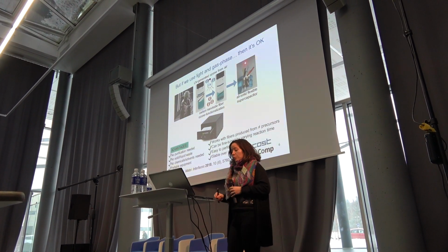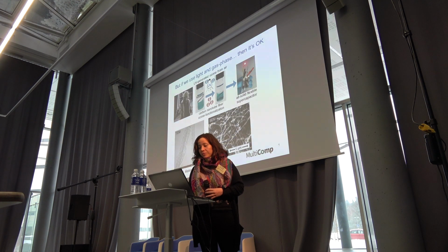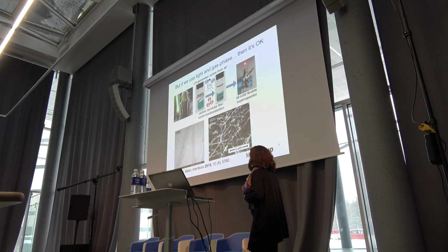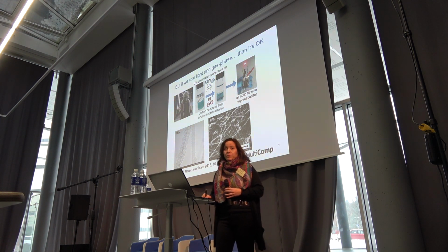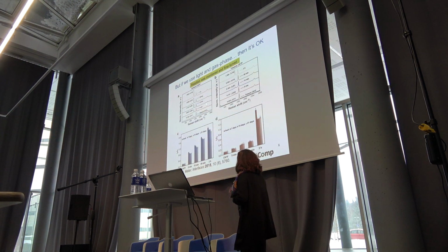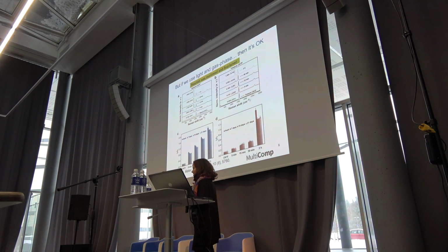And we have characterized the material by a number of different techniques. Here I'm just showing that SEM still shows the presence of the tubes. By high resolution TEM, you can see that as you progress with the functionalization, you do introduce defects into the sides of the nanotubes, as expected. And this was applied to two different kinds of carbon nanotube fiber produced from butanol as a precursor or from toluene as a precursor. The two fibers have different levels of pre-existing defects.